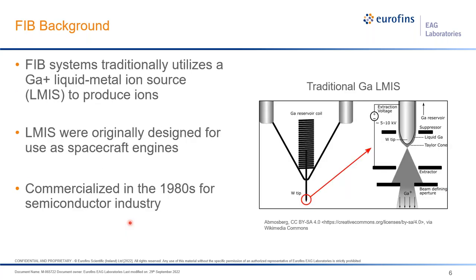A little bit of background about FIB. FIB, as the name suggests, utilizes a focused probe or beam of ions to modify a sample. FIB systems have traditionally utilized gallium liquid metal ion sources, or LMISs, to produce these ions. Interestingly, the LMIS was originally designed for use as spacecraft engines, but it eventually found commercial use in the semiconductor industry starting in the 1980s.